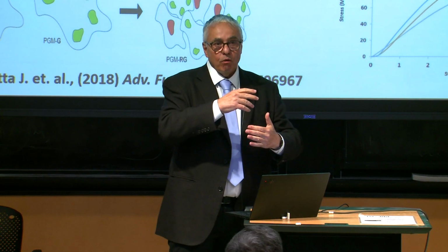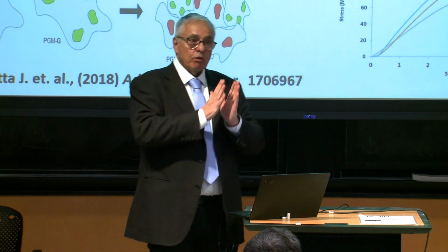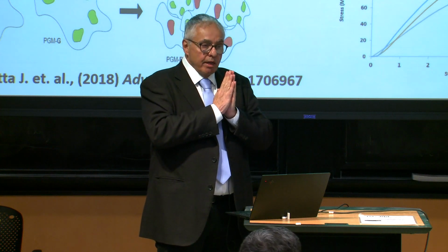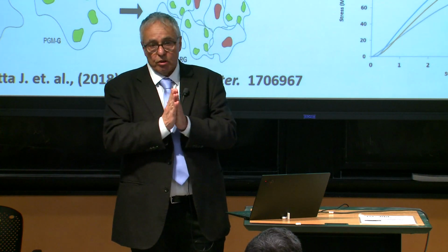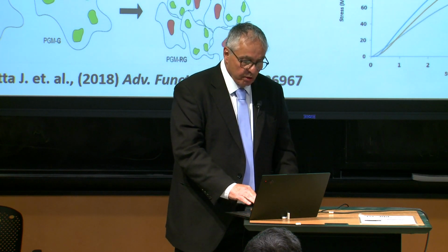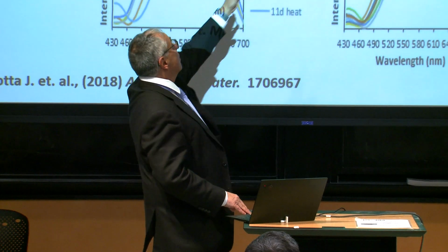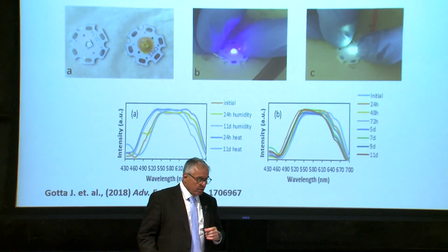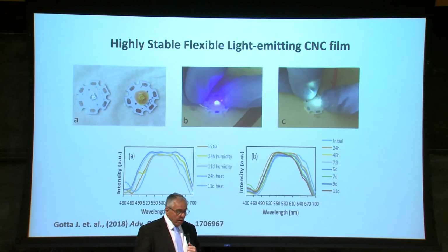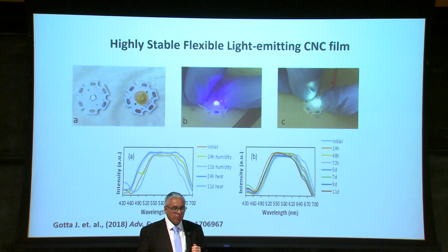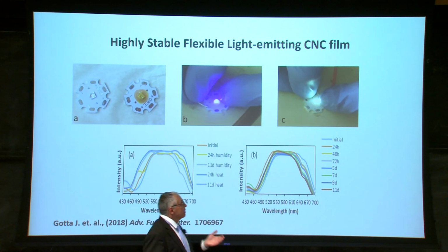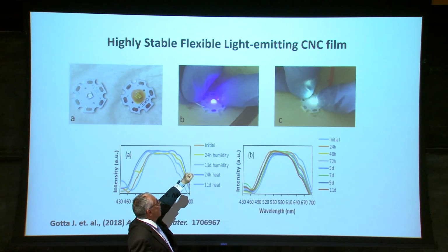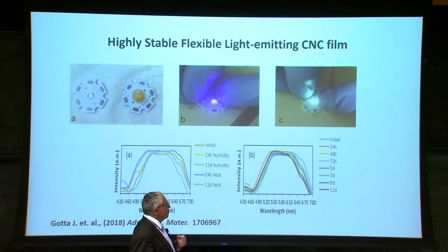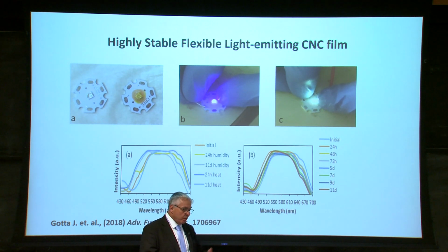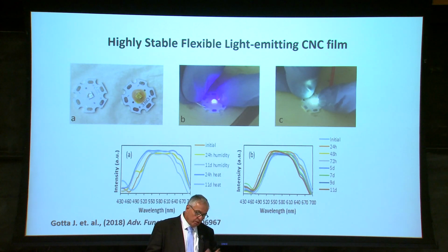And now mix all that with cellulose nanocrystals and make a film. The cellulose nanocrystals hold them in an environment that is very protective from oxygen. So the material that we got is quite flexible, and you can see here, on the left, a regular LED. Next to it is one that is coated, and you can see for yourself, the uncoated has this blue light, while the coated has a really nice white light. We tortured it for a long time in different temperatures and also humidity, and it performed really well.